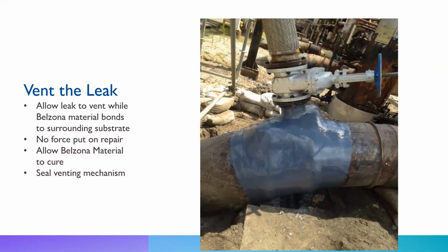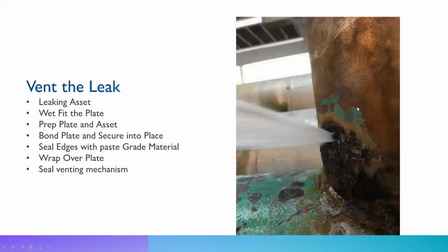So one thing with the vented leak is you do have to have a way of diverting the flow. So as you can see, this is another application here. Tight corner on a T, coming out pretty hard. You have some pretty poor metal around the leak. So if you try to plug this or really compress it with a clamp or something, you might make the hole even bigger and you might have more issues.